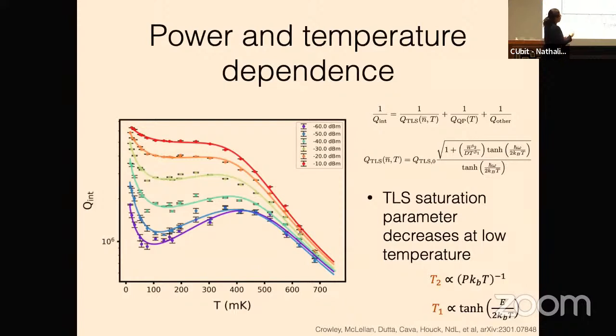the data. So we say that our quality factor is a sum of the TLS component, the equilibrium quasi-particle loss as you go to high temperatures, and then something that is power and temperature independent that we don't see in this data that stops you from getting to a Q of infinity at high power. And this all gives you something like 7 free fitting parameters, and we can just fit this entire data set and get a quite beautiful fit to the whole data set.